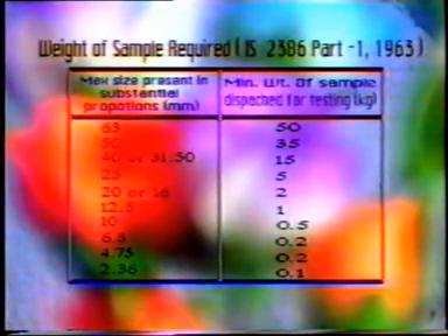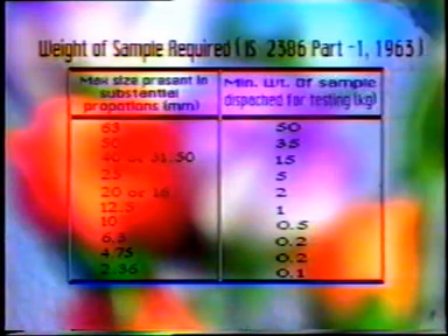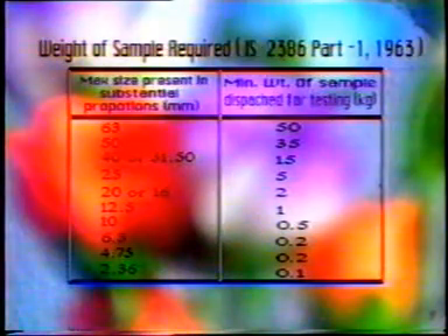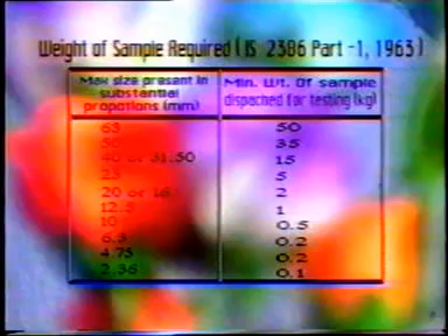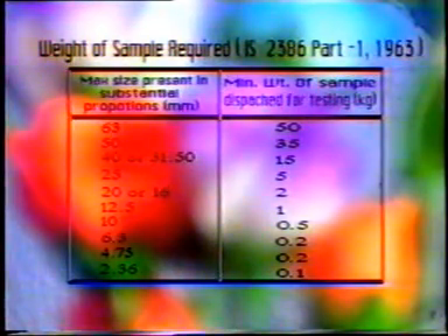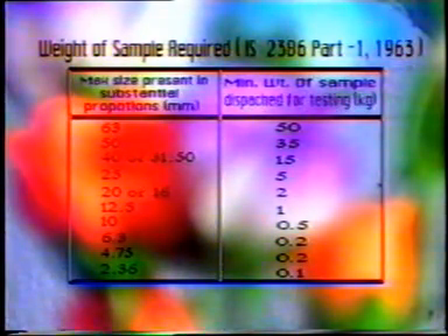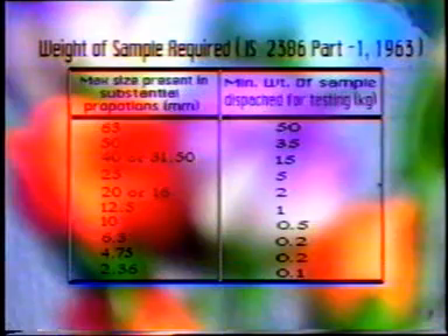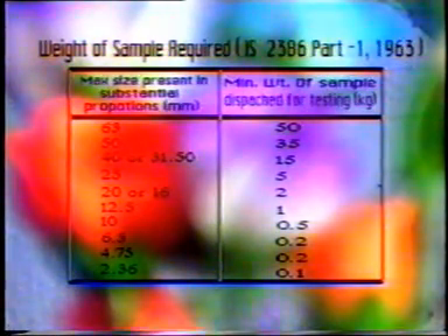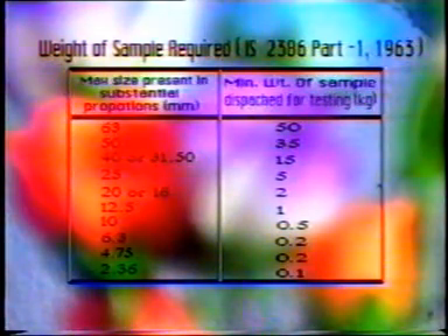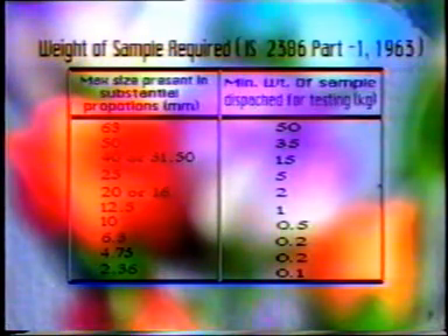Minimum weight of sample to be tested for gradation of aggregate as per IS 2386 Part 1 1963 is as per the table shown in the IS code. For maximum size of aggregate 63 mm, the minimum weight of sample should be 50 kg. Like that, for a minimum size of aggregate sample, for an aggregate size of 2.36 is given in this table. Material preparation. Material is oven dried at 100 to 110 degrees centigrade for 4 hours before the sieve analysis or gradation is done.